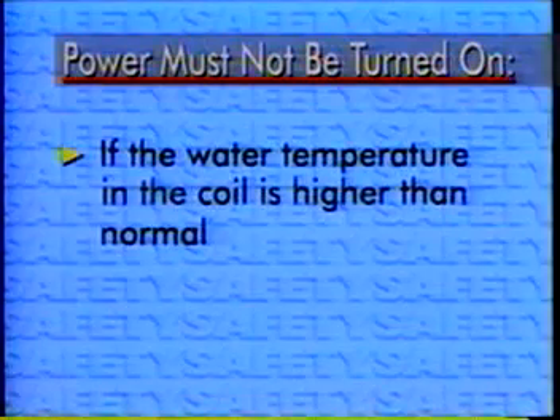if there is excessive surface slag visible, evidence of serious lining damage, or if the water temperature in the coil is higher than normal. Each of these conditions indicates that molten metal may be next to the coil and requires an immediate evacuation of the area until the metal in the furnace has completely solidified. If none of these conditions exists, the melt can continue.